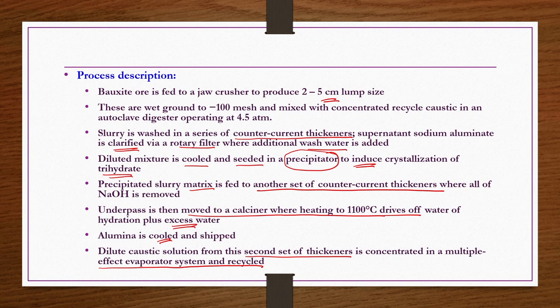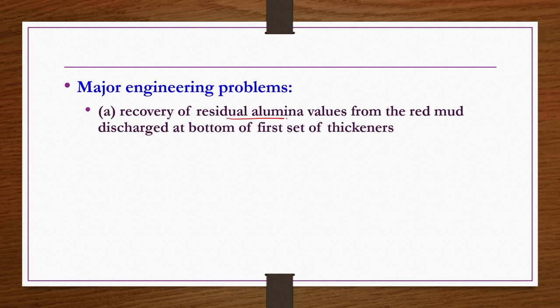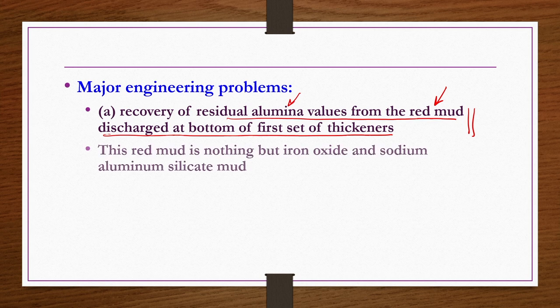What are the possible major engineering problems in this alumina purification process? Recovery of residual alumina values from the red mud discharged at the bottom of the first set of thickeners is very much essential, because whatever the red mud, as I mentioned, you cannot throw directly, you cannot discard, because the thickener processes are not so effective that they completely separate the red mud from the sodium aluminate. So that red mud may also have some amount of alumina, so you have to recover it. So that recovery is one of the important problems.